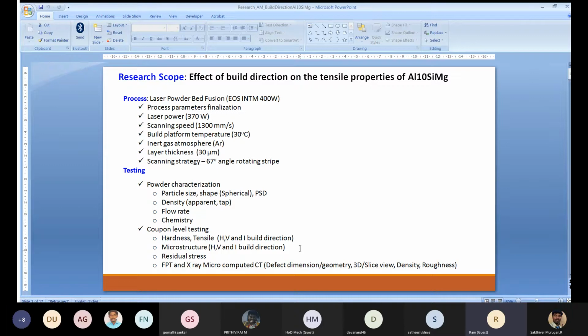And to understand the defects inside the component, we did fluorescent penetrant to inspect the surface, and we did X-ray microcomputer tomography to understand the internal defects. We don't use radiography, we use computer tomography. The advantage is you get a 3-dimensional image, which also tells you defect dimension and defect geometry, and you have a provision to understand the cross section of the defects through slice views. In addition, you can get the rough density, because you are able to get all the porosities. So theoretical density minus porosity will give you the density, and you can also understand the surface roughness from the X-ray computer tomography.